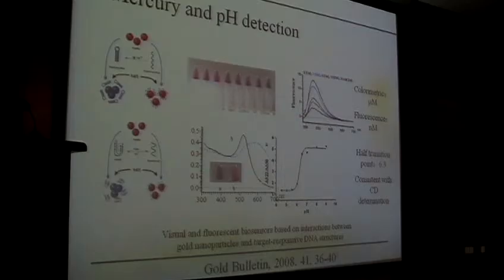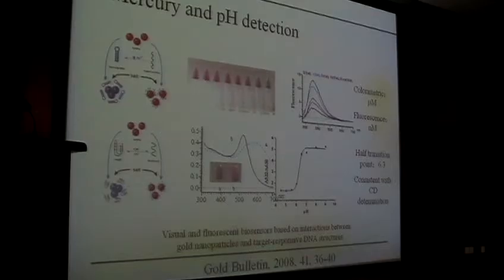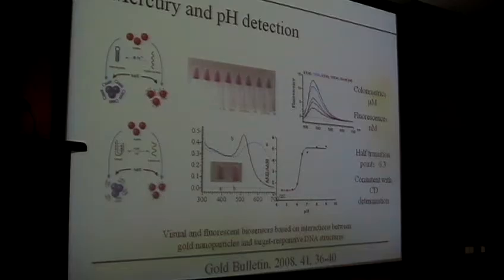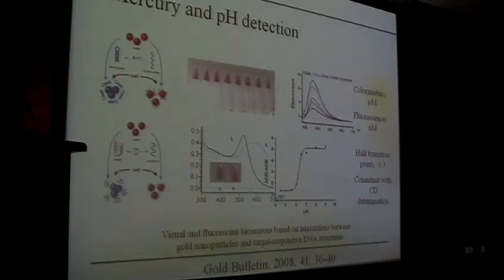This method can be extended to the detection of other metal ions — for example, mercury, which binds specifically to thymine-rich DNA strands. We can see the color change gradually from red to blue along with the increase of mercury concentration. There is also an i-motif structure that responds to proton pH values, and we can see the red-to-blue difference consistent with CD spectra determination.